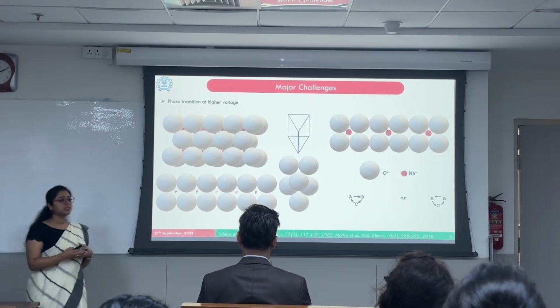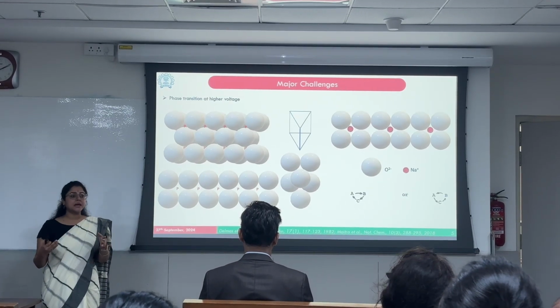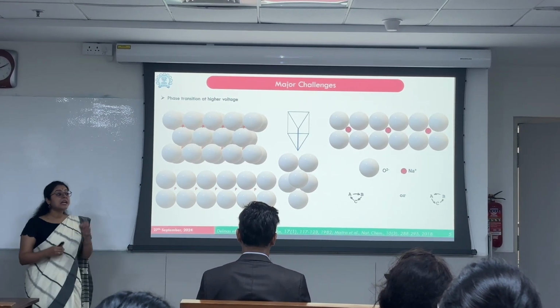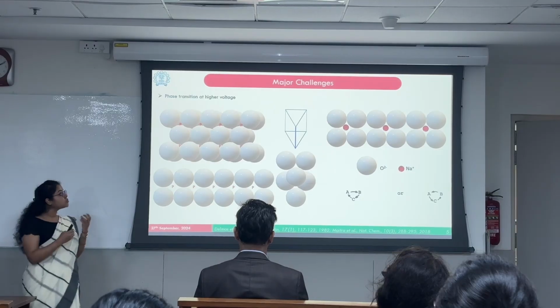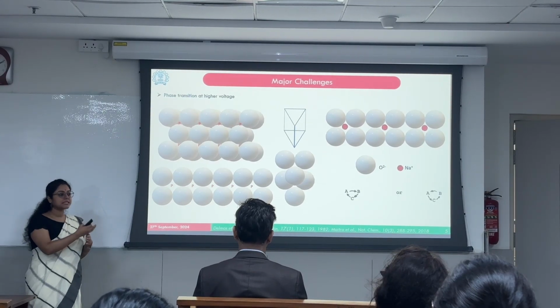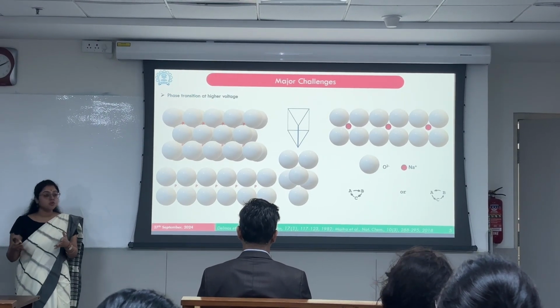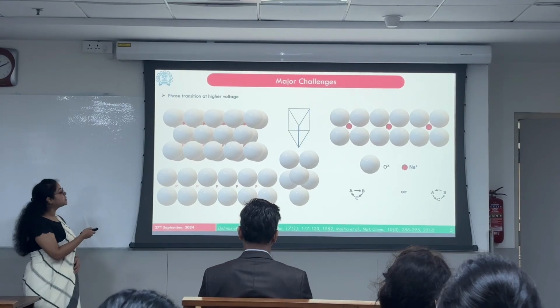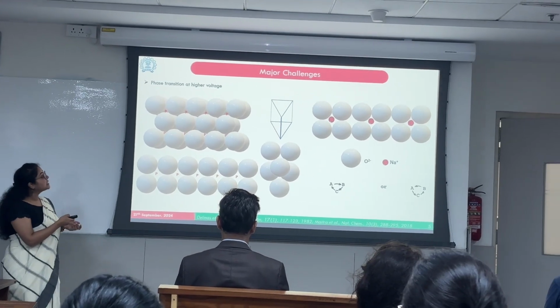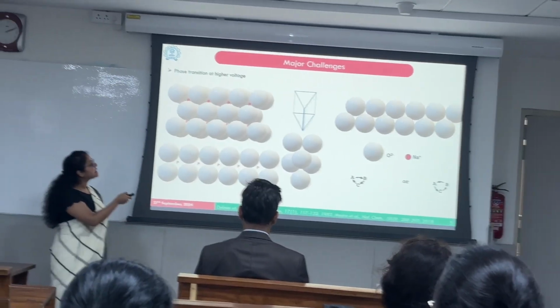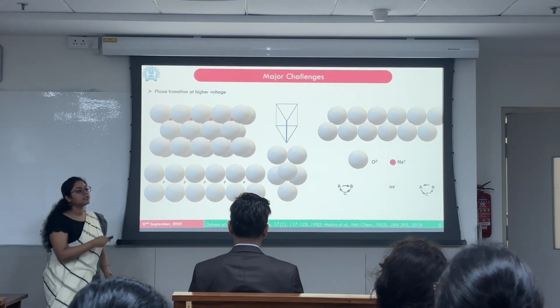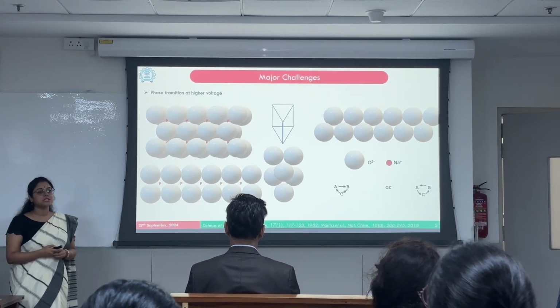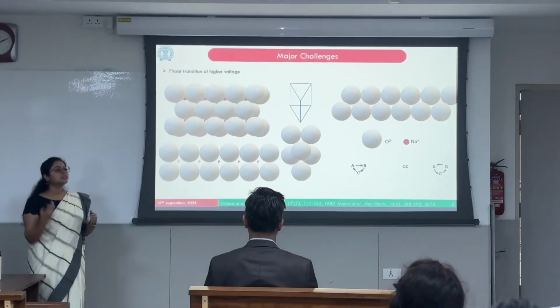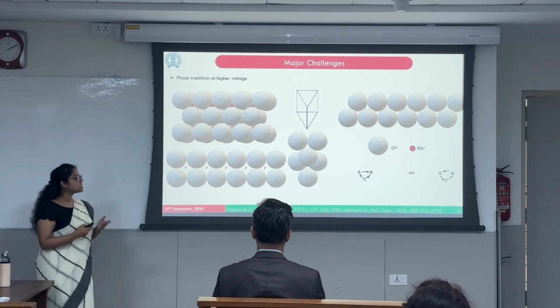Thus, a prismatic void is formed out of 6 anions, which looks like a trigonal prism. So during charging, when we are extracting the sodium ions from the cathode material at a higher voltage, when the amount of sodium ion reduces from 0.67 to 0.33 to 0, because of the weakening of the electrostatic cohesive forces, the slabs of the transition metal glide and form octahedral voids instead of prismatic voids, making the reinsertion of sodium into the cathode material difficult.